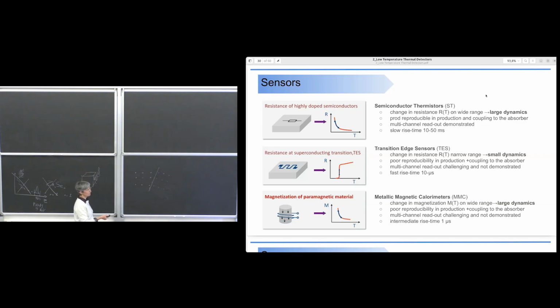It shares with transition edge sensors the problem of reproducibility and readout, because again it is a low impedance device and needs SQUIDs for the readout. And the rise time is in between that of semiconductor thermistors and that of transition edge sensors. I think mainly because in that case you do not have a film on the crystal. On the crystal, you have something that we call a phonon collector. In that case, it is made of gold, and then you have a thermal connection to your system.